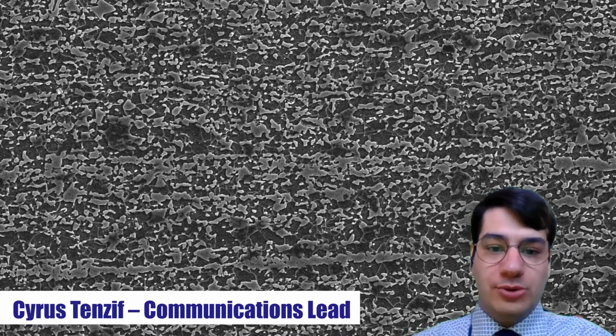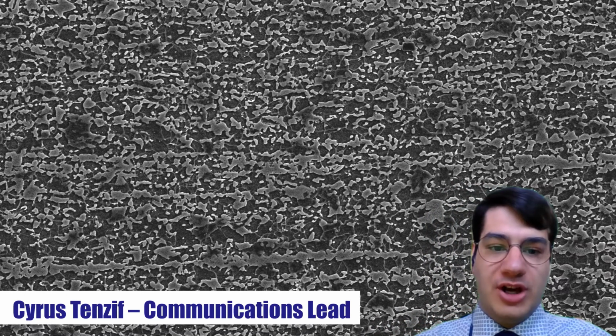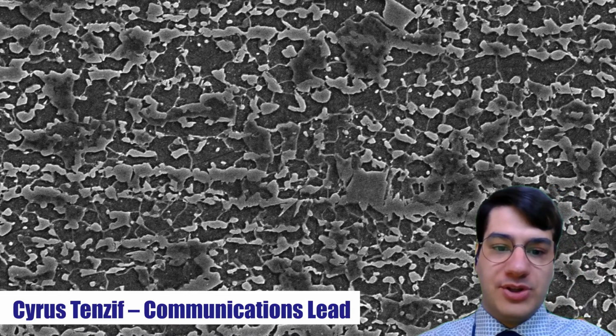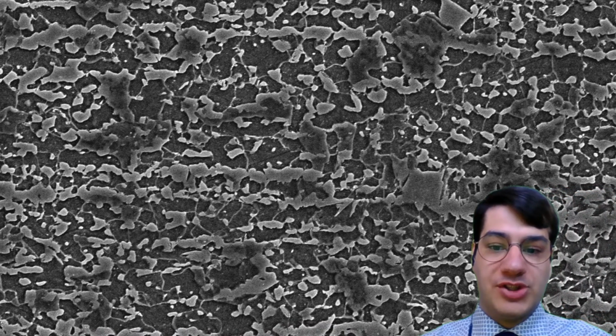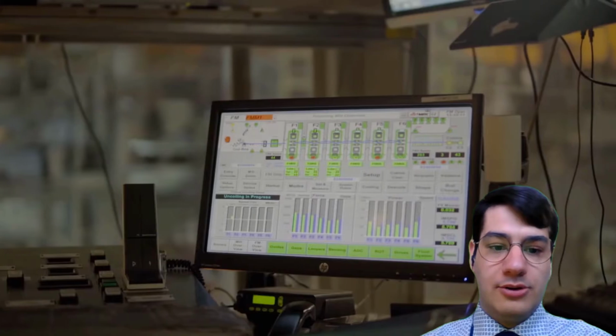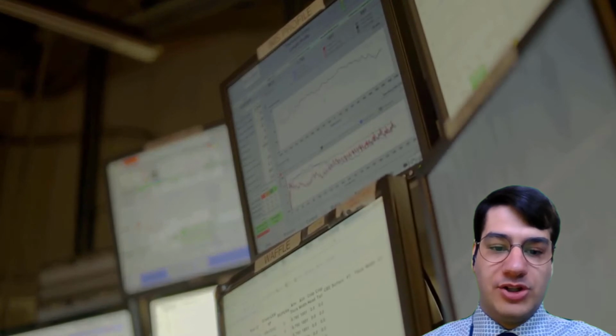A prominent issue leading to decreased bending performance identified through microstructural analysis was centerline segregation. Put simply, too much of the hard martensite phase was clustering along the center of the steel, resulting in the formation of cracks. The current alloying chemistry of the steel is believed to be the cause of the centerline segregation.